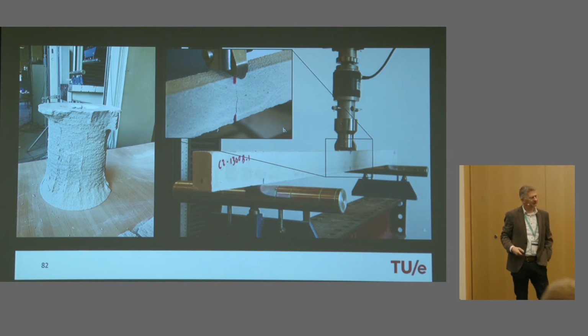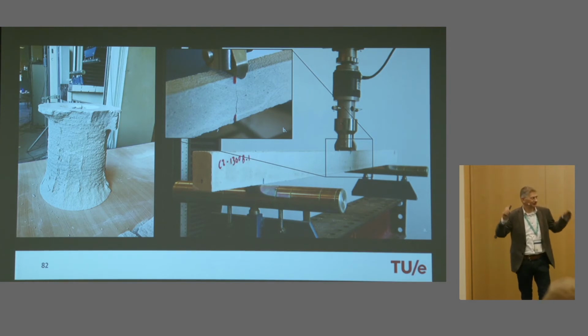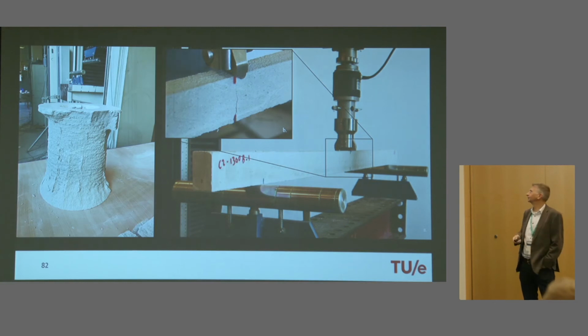That was the reasoning that I did this. But to my surprise, it also worked in a beam as a reinforcement wire. Have a close-up look, you can see there is a crack, there's my compression zone, and it simply works as reinforcement as well. That came to me as a surprise. I never intended to do that.